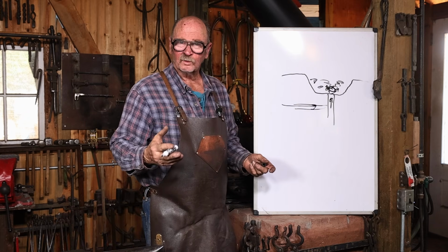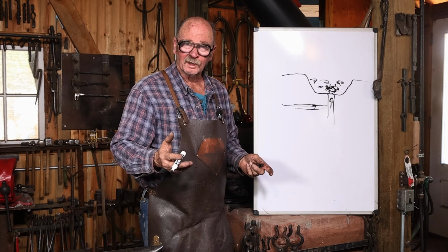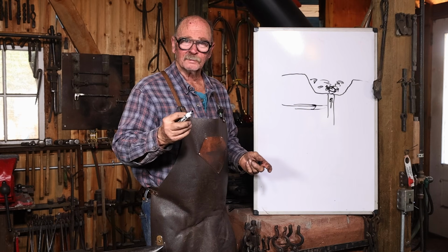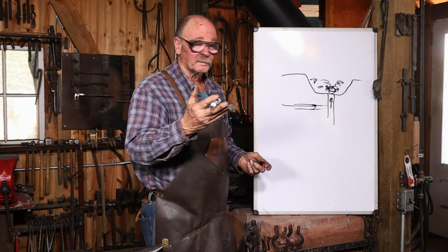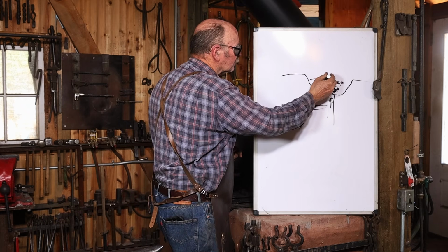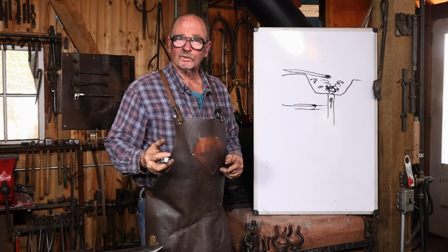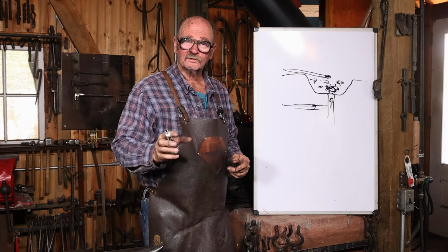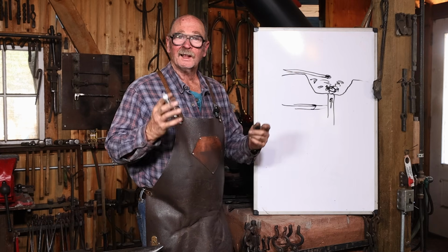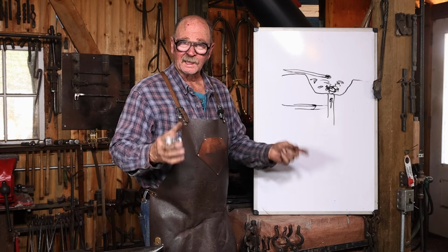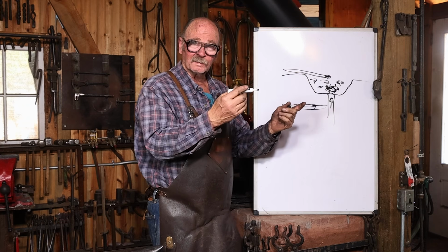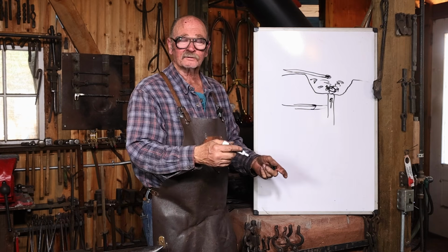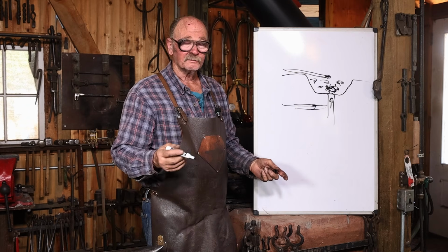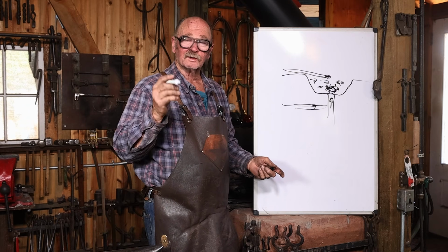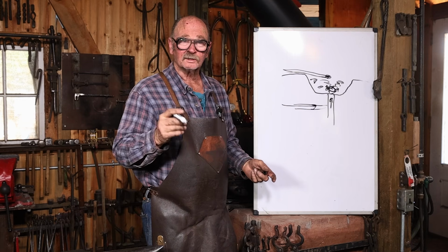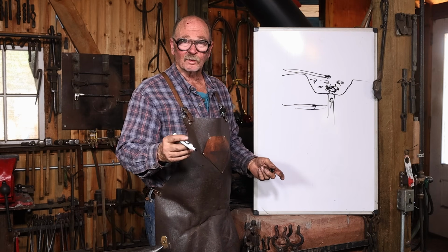If you have a riveter's forge or something like that that doesn't really have a fire pot, you may not be able to get your material up high enough to be away from the oxidation. Right in this area though, is where you want to put your material for forge welding. The oxygen should be consumed by that point, and that should have the maximum amount of heat right there. You go higher than that, it's not going to be quite as hot. Go lower than that, you're going to start oxidizing, and you can actually burn material. If you see a lot of sparks when you're forge welding, you either got it too hot or had too much oxygen, and you could actually burn it even though it isn't quite up to heat yet.